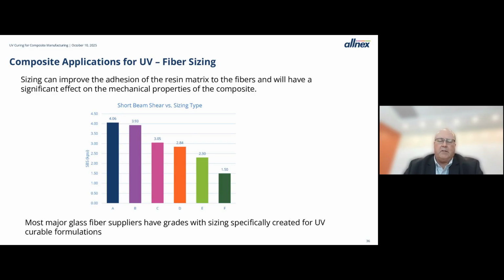And finally, and this I think we all know, fiber sizing has a big effect on physical properties of composites, and UV curing's no different. So what the chart here shows is the short beam shear strength versus different sizings on the glass fibers. And you can see a considerable difference in the strength of these materials based on the sizing alone.